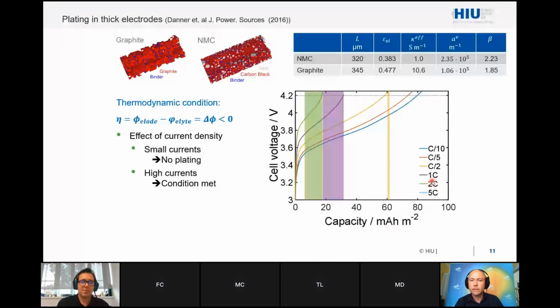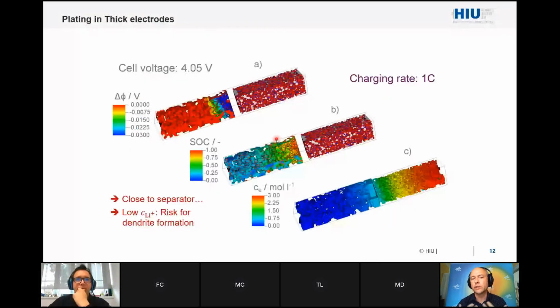At 1C, we lost a lot of capacity, and over a large range, we found plating somewhere in the electrode. And if you get to 5C, for example, it's not even in the plot anymore, since we get plating immediately all over the place. The interesting question is, of course, where is this plating going to occur? And here you see immediately the impact of the inhomogeneities, which I mentioned in the beginning, which were produced due to this operation. If you look here at the electrolyte concentration distribution, you find enormous depletion of electrolyte in the anode regime, since upon charging, the anode is sucking up all the lithium ions, and only some lithium ions remain close to the separator.